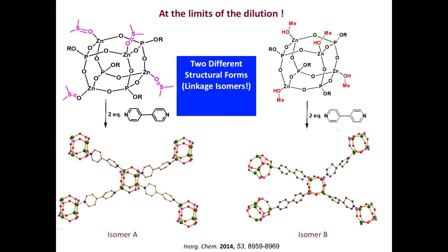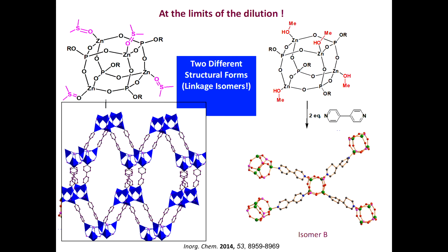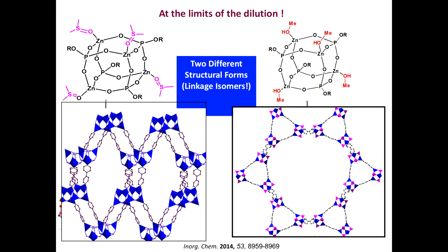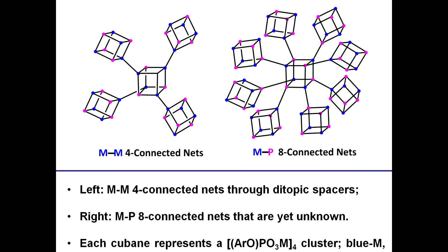So depending on the cubane to cubane to cubane angle, which is acute or obtuse, you can form either a diamondoid structure such as what you're shown here, or you can form something like a Kagome type of lattice. So you have essentially 3 cubanes forming a micropore, and 6 such edifices forming a mesopore or a macropore. This is about 24, 25 angstroms, and this is about 7 angstroms. So essentially you have a mesopore and a micropore within the structure. We have used it for catalysis and other things. I would probably leave it for some other day.